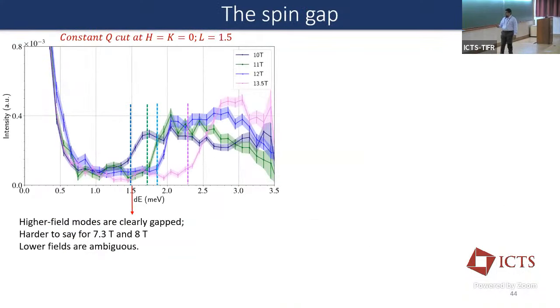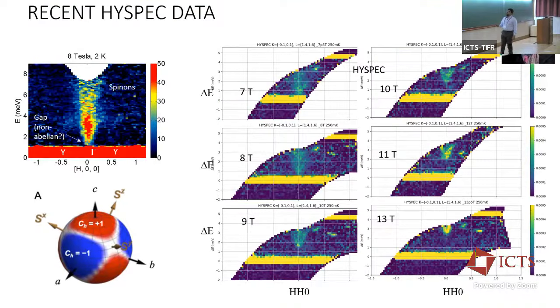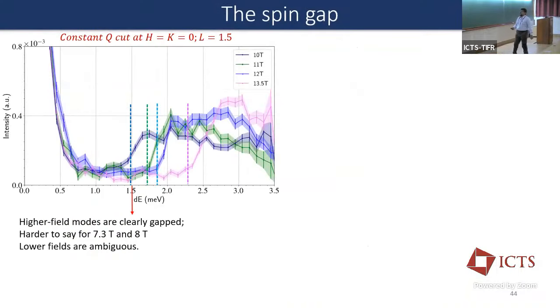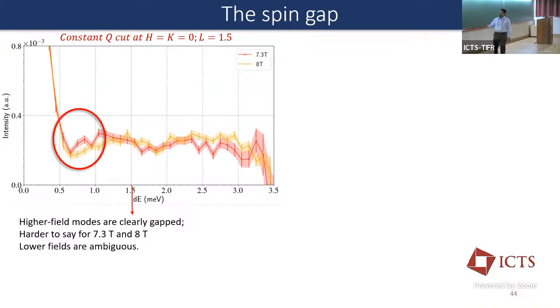But then we try to understand, okay, is this gapped or is this not gapped? Now, this is not background subtracted, but it turns out that background subtraction is extremely necessary here. For high fields, of course, we don't need to go through any background subtraction. We can clearly see that we have a gapped mode, which at 10 Tesla, the gap is roughly 1.5 meV. At 11, it's roughly 1.7. At 12, it's roughly 2 meV, and so on and so forth. But at low fields, which is 7.3 and 8, which is a very interesting regime, we were trying to understand, okay, is that really gapped or is that really not gapped?